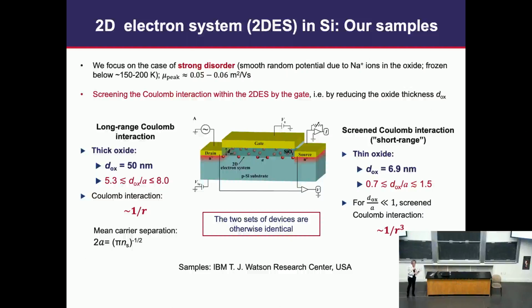So we looked at devices where the disorder is sufficiently strong. For MBL, we need strong disorder. We looked at two different sets of devices. The important thing is that they were fabricated at the same time, so all the steps are identical. The only difference is in the thickness of the oxide.